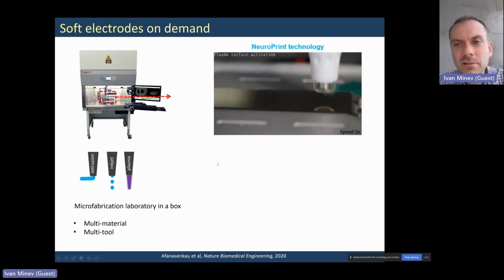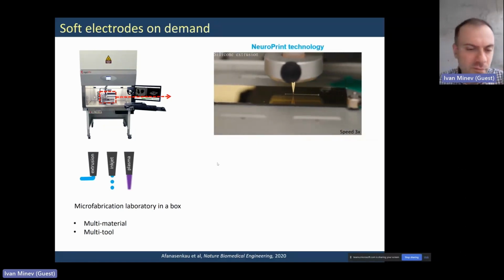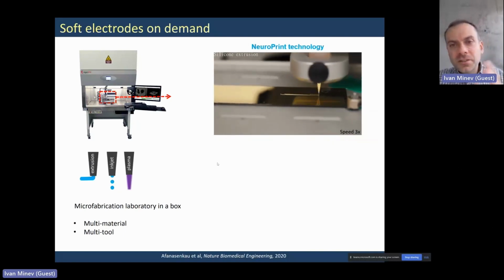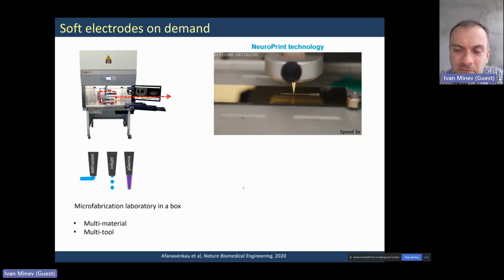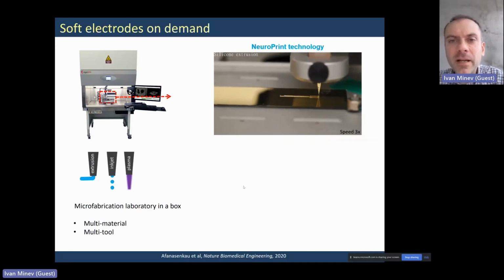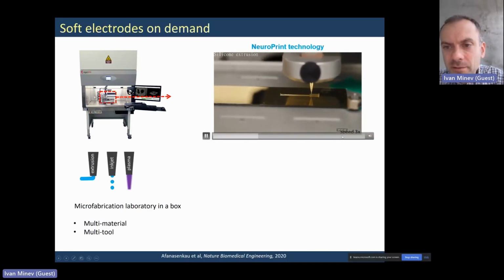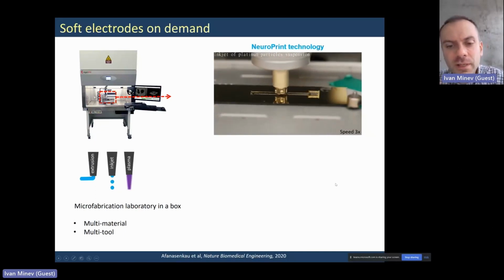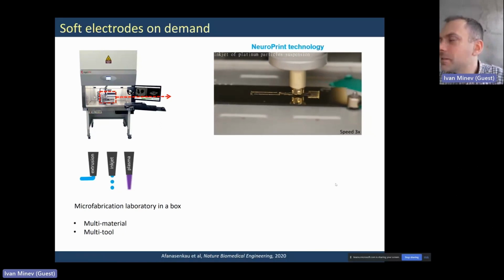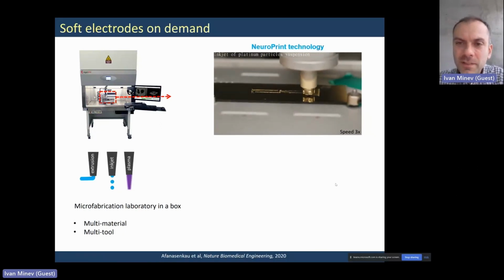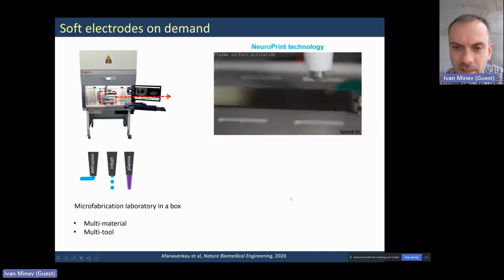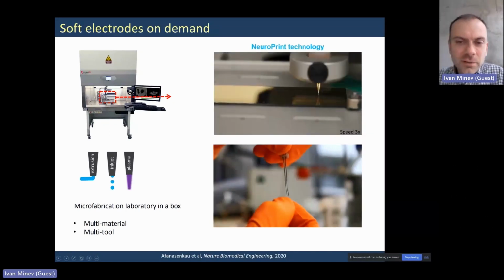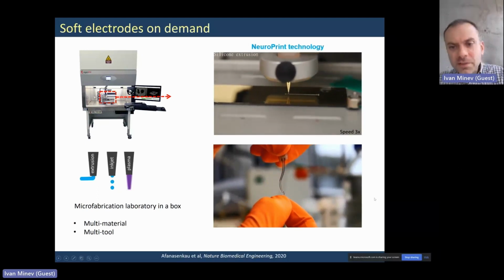Here you see a small video of how we use the various tools. The first thing you saw is how we can expose the surface to plasma. This is simple extrusion of silicone that defines essentially the insulating parts of the electrode arrays. And then if we zoom forward now, we switch to the print head, where we form droplets of the conductive ink, and we fill the channels that are formed between the silicone tracks to form the electrical conductors. And then the finished electrode array might look like this.